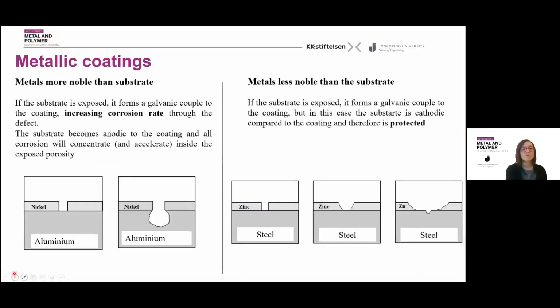Just be very careful, because if you choose metallic coating for your final finishing, you should be really careful about their behavior in case of defects. Be careful, because if you put a metallic coating that is more noble than aluminum—and in the case of aluminum, most of the other metals are more noble, since aluminum is not so noble—